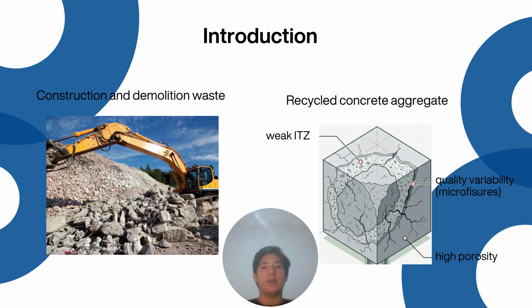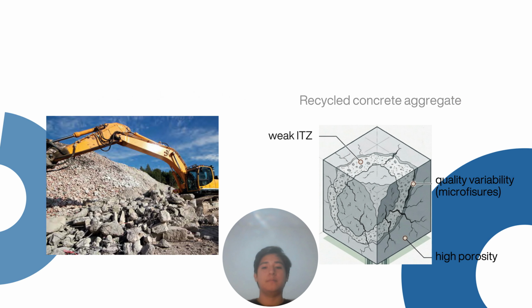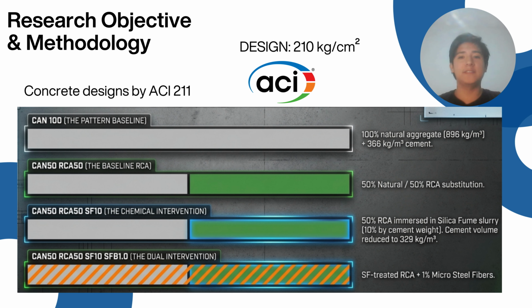Although recycled concrete aggregate is a promising sustainable alternative, its application is often limited because it reduces the compressive strength of concrete. Therefore, our research aimed to overcome this limitation by treating the recycled concrete with silica fume slurry and reinforcing the concrete with steel fibers. The objective of this study was to evaluate whether concrete containing 50% recycled aggregate could achieve equal or better performance than conventional concrete while reducing environmental impact.